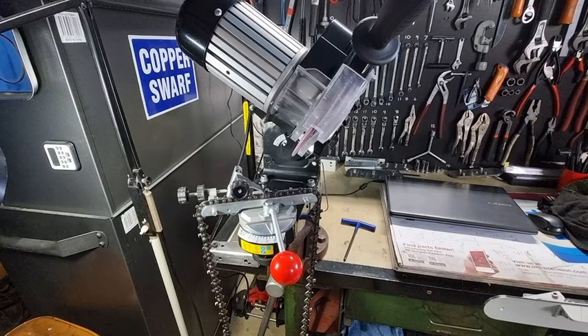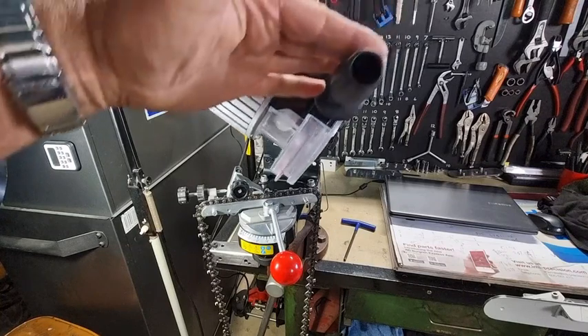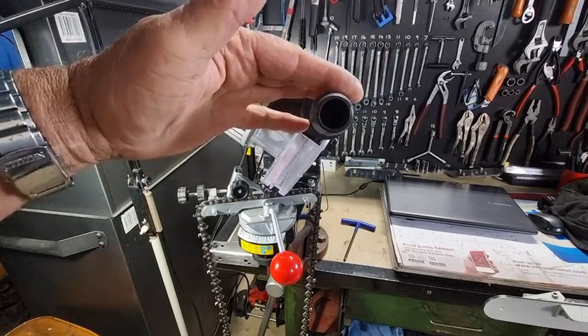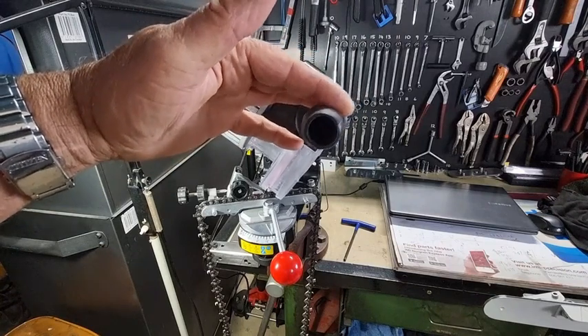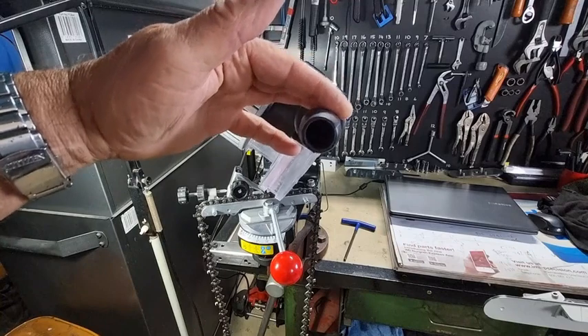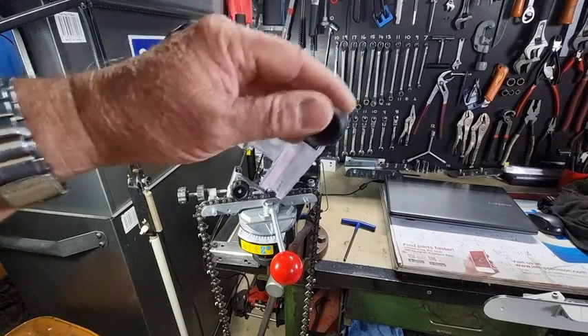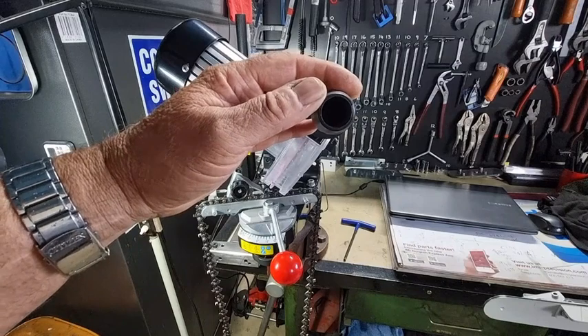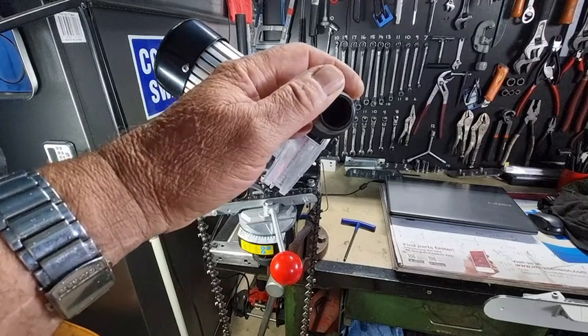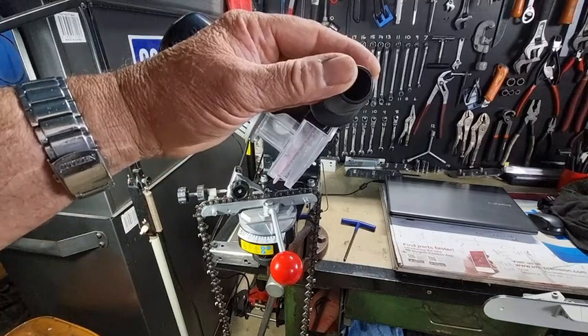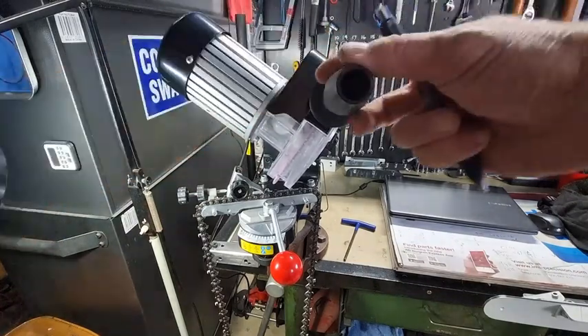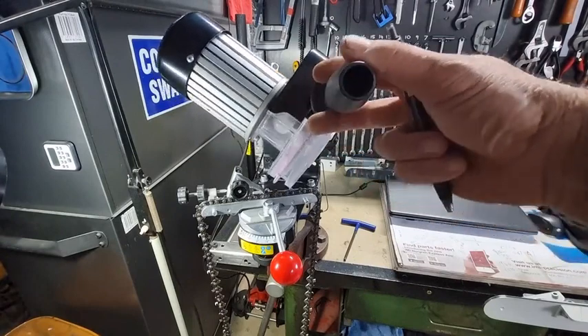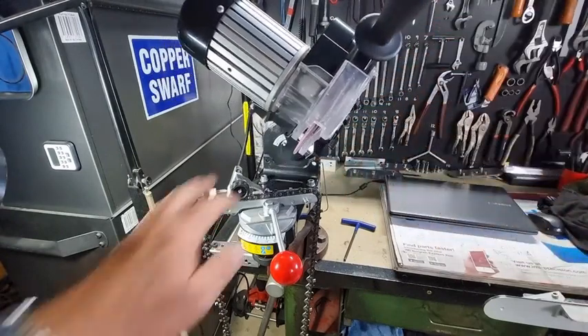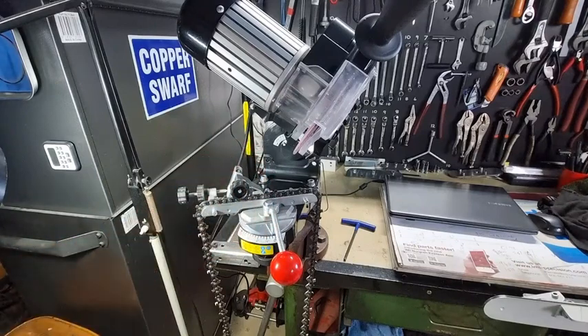The only thing that I would say to avoid any bluing of chainsaw chain using a grinder is that when you bring this down, the moment that it touches the tooth, you just touch it a little bit like that. Just tap, tap, tap, tap, off, on, off, on. Don't want to be going too fast like that, because if you go too fast, then you're not giving the metal or the tooth a chance to cool down. And it's only being cooled by air, and it cools down fairly quickly. So off, on, until you reach the bottom, and you should be able to put your finger on there. That's how you can gauge that you're doing it correctly.